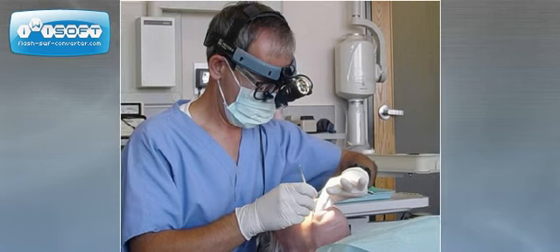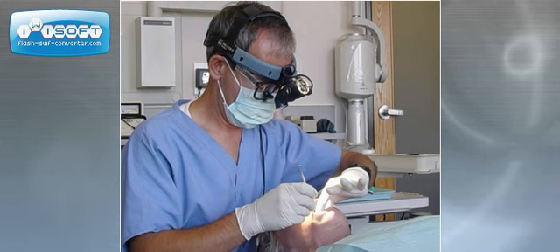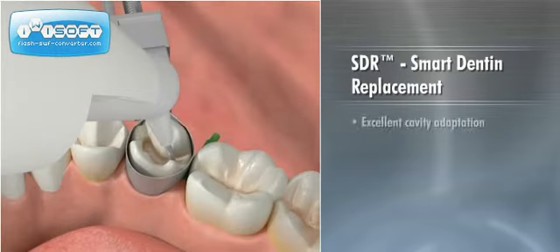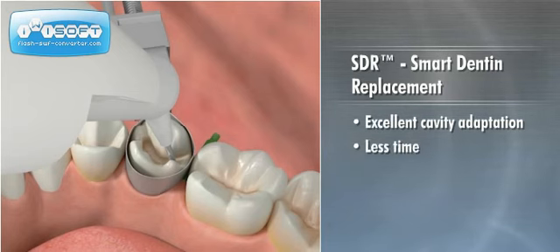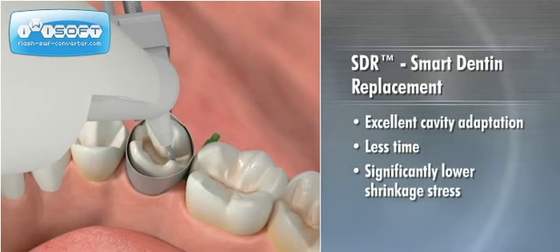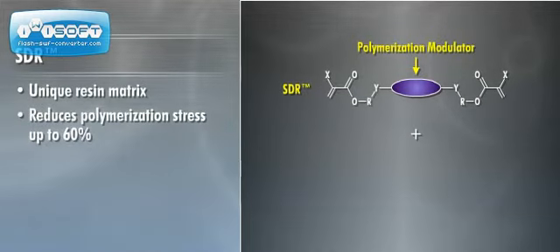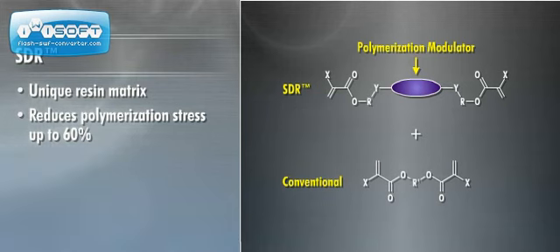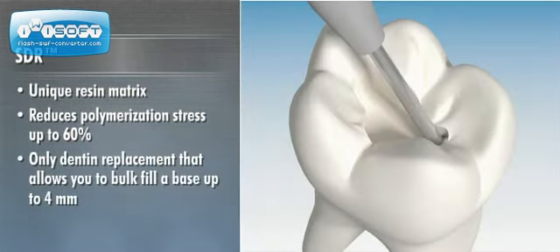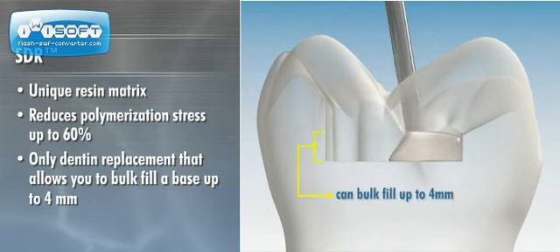For years, dentists have optimized their procedure for posterior composite restorations by using a flowable composite to improve the cavity adaptation in difficult situations, followed by complex layering of the universal composite to control the resulting polymerization stress. With SDR, you can enjoy excellent cavity adaptation in less time and with significantly lower shrinkage stress. SDR's unique resin matrix reduces polymerization stress up to 60%, and it is the only composite material that allows you to bulk fill a base up to 4 millimeters.